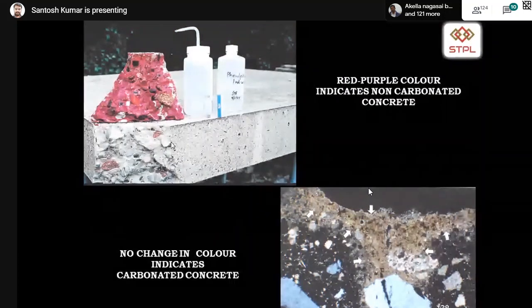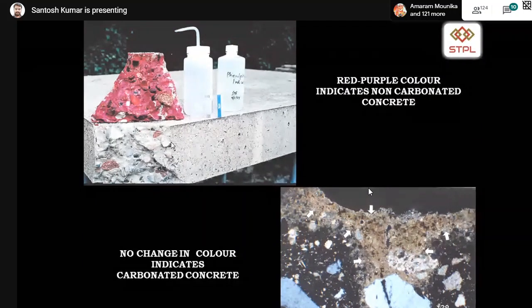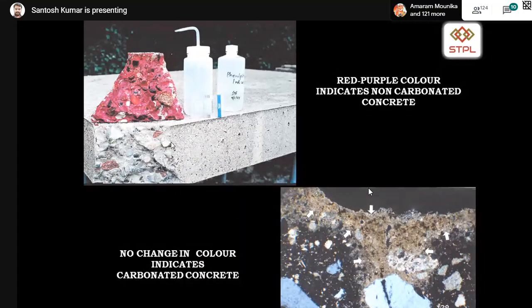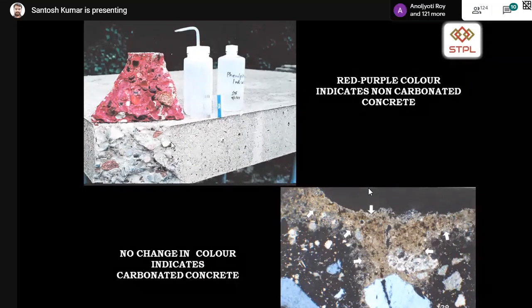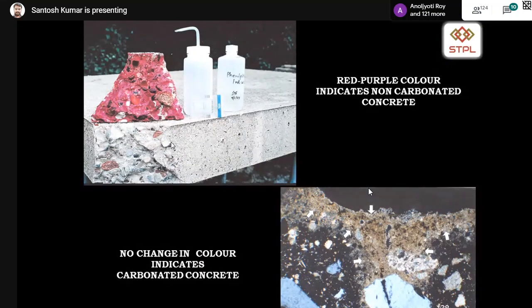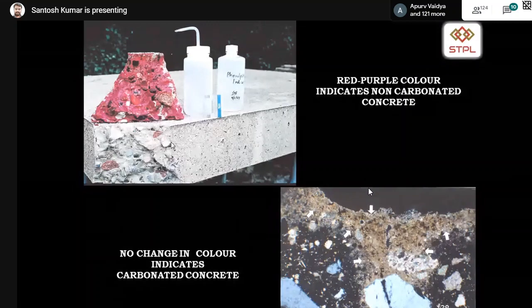Now, if you spray the solution, the concrete turns into pink color. Pink, I can say red-purple color. Immediately before 30 seconds, if it is changing the color, then your concrete is alkaline. It is not carbonated. If there is no change, the concrete is carbonated and your concrete is sick.